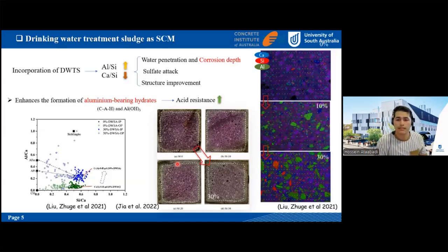One of the applicable methods of reducing the impact of sludge is to use the sludge as an SCM in cementitious material. This is the work my group has been doing over the last 5 years, and we have had a lot of achievements. Once we incorporate the sludge into the cementitious material, because of its aluminum and silicon content, it changes the aluminum silica ratios inside the cement matrix, and it can reduce water penetration and improve the corrosion resistance of the cementitious matrix. So definitely it improves the structure of the cementitious material.